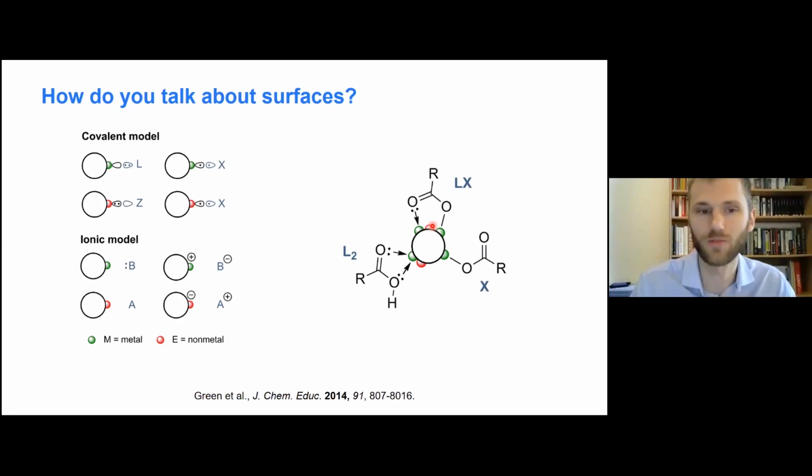So like I said, we don't have the spectroscopic tools to actually look at how the surface atoms are reorganized when you do a ligand exchange. The only thing we can do is calculate it. If we think about Ivan Infante's hypothesis, where it's the two-coordinate selenium that is actually causing this trap state in the band gap, then maybe there is some way that the phosphonic acid causes that. I don't know. It's a good question, but it's hard to have the answer to that because we just don't have the spectroscopic tools.